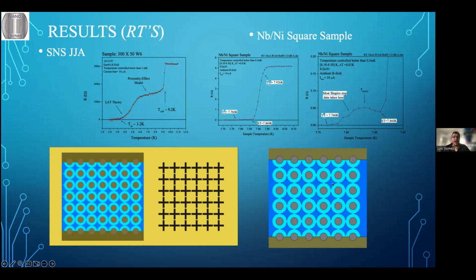So these diamonds are like squares, pockets of fully superconducting niobium. This is just niobium, which I measure below the transition. That's why I had this very sharp transition temperature. So I got this region here where there is the tunneling. But I also take a look at this graph and this graph. There is some similarity right there. There is a temperature below which there is zero resistance, the same as here, but there is a region here where there is actually a resistance in the system.